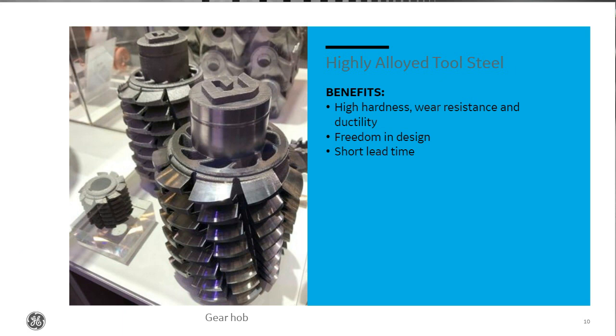We actually have two different gear hobs, one minor and one larger one. Basically the larger one is most interesting, because here we also have the cooling channels that Isaac mentioned that we could add along the process, where we can have internal cooling channels for when you're using the hob. And we have the possibility with our process to process this crack-prone material that no other AM technique can do at this point. So we have a really hard material that we have been able to produce with our technology.